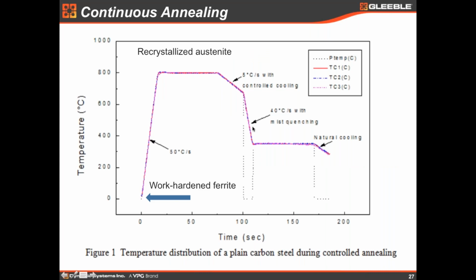So you have information about the microstructure and also mechanical properties by running the test offline and avoiding a huge experimental cost to understand what's going on in the actual line. So this is another very important use of the Gleeble. Of course, we have a work-hardened ferrite. Most of the time we have a work-hardened material or a deformed coil, and we have recrystallization happen in the first plateau. And after that, of course, depending on the cooling cycle, you have the formation of the phases that you want to form.